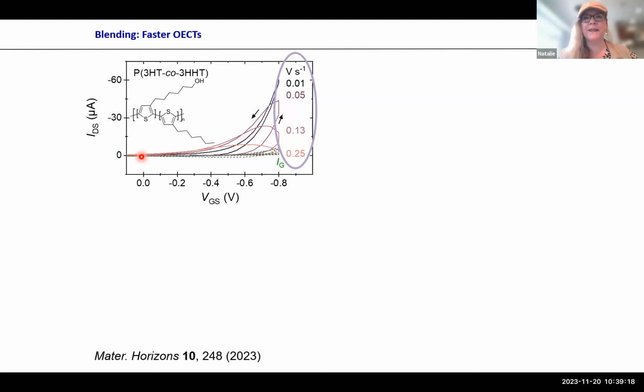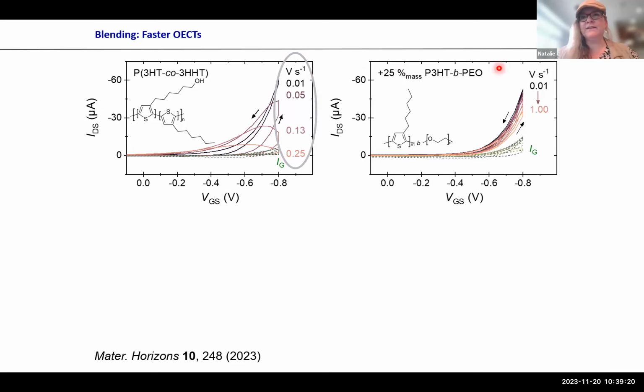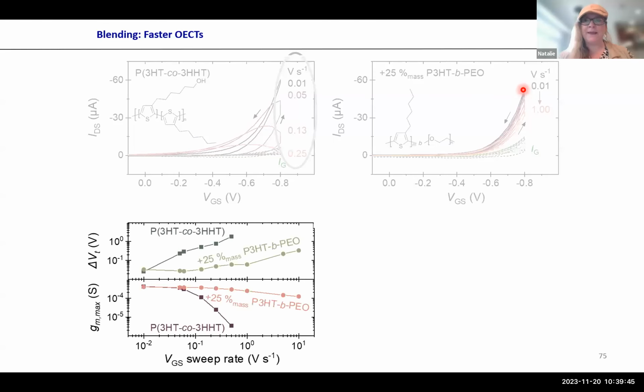So they're too slow. When you do now that with some of the block copolymer, so we added 25 weight%, you see we can even go super fast with 1 volt per second, and we still have essentially no hysteresis. So that tells us adding the block copolymer helps in getting the ions in as well as getting the ions out.